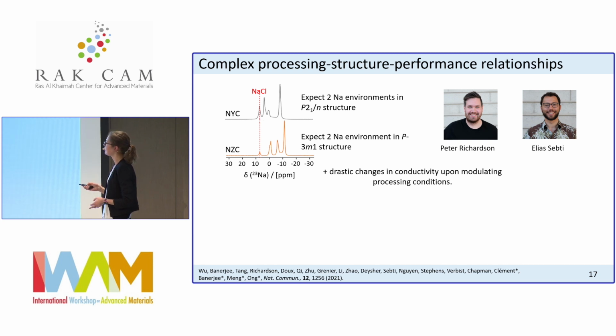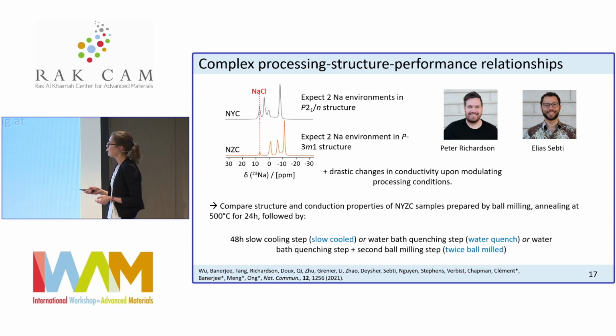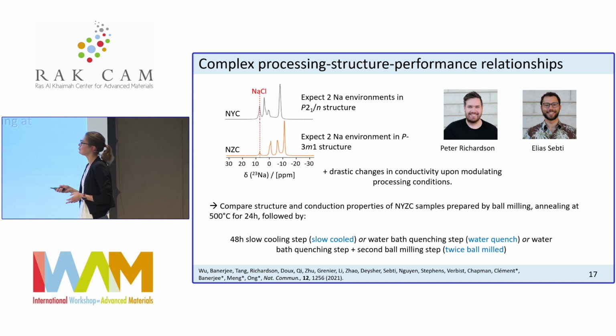Plus, we found that the conductivity that we were measuring was drastically changing if we changed processing conditions only slightly. And so this led us to perform a follow-up study where we looked a lot more in detail at the relationship between processing, structure, and conduction properties in this family of compounds. And so we synthesized basically the 2 end-member phases and the 75% zirconium-doped phase using a first ball milling step and annealing at 500 degrees Celsius, and then 3 different conditions.